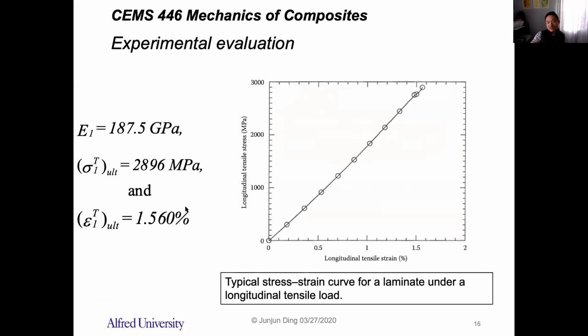So this is the typical stress strain curve of the laminate under longitudinal tensile load. This is the experimental data. Okay, so in this way, you can easily find out the Young's modulus, right? Because Young's modulus is actually the slope of this linear curve, and the ultimate stress is the maximum stress shown here, right? And this is also the maximum strain. It should be a straight line. So to measure them experimentally, it is really easy to get a stress strain curve.